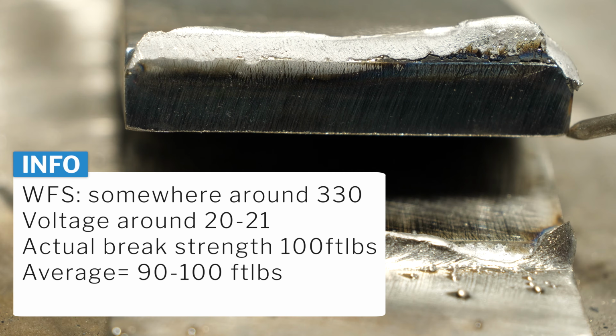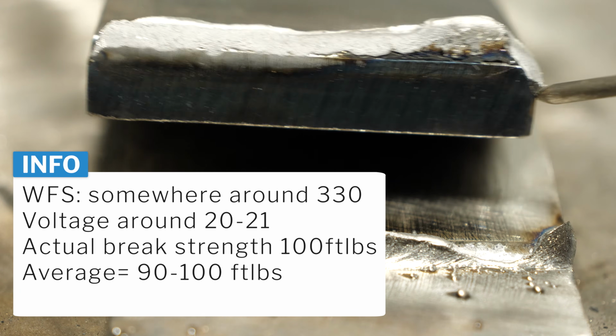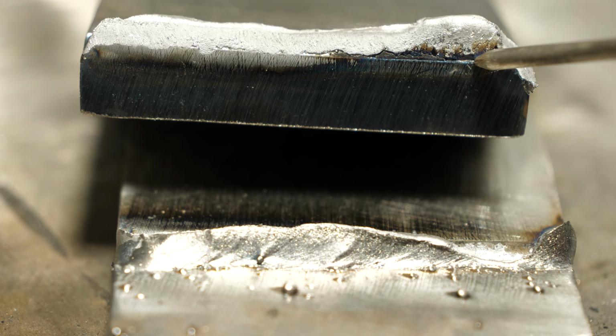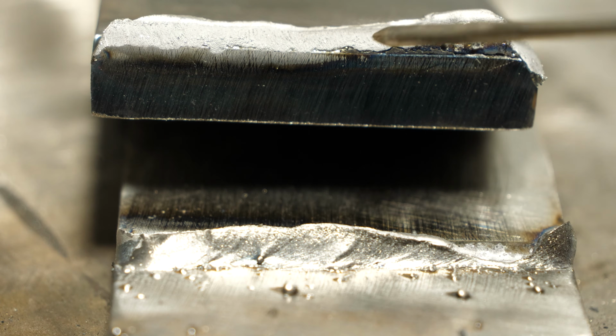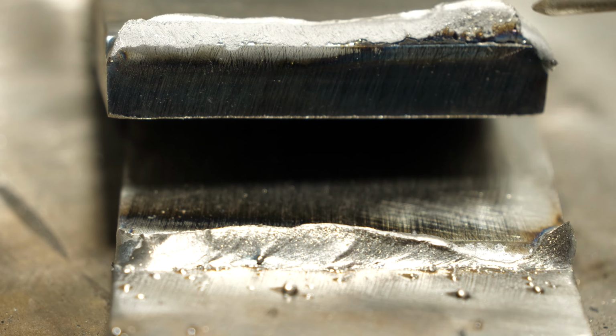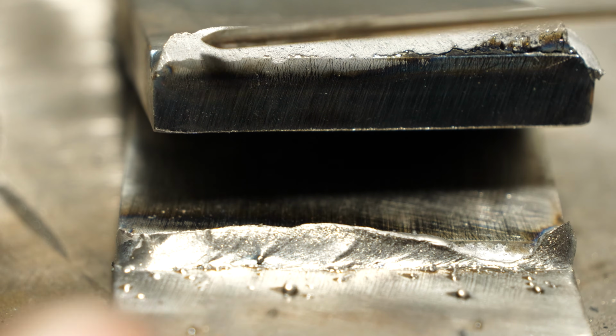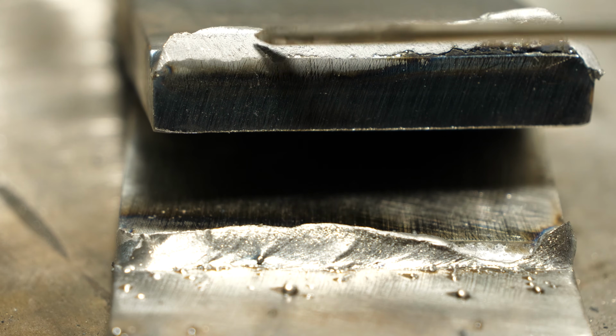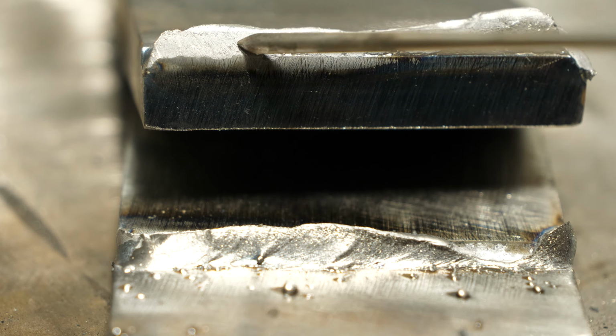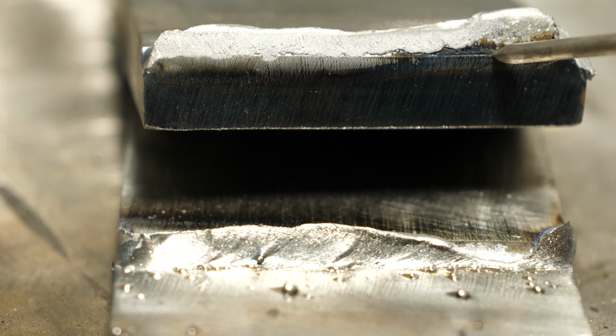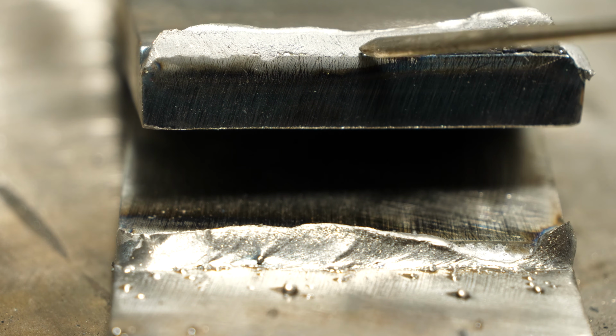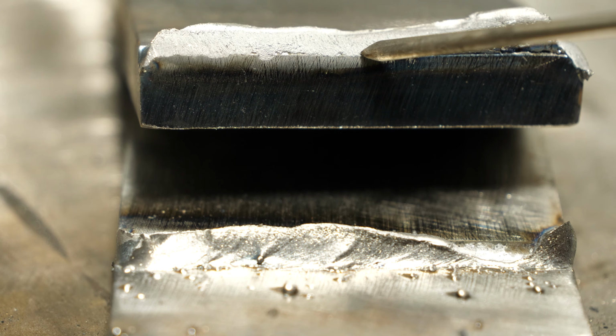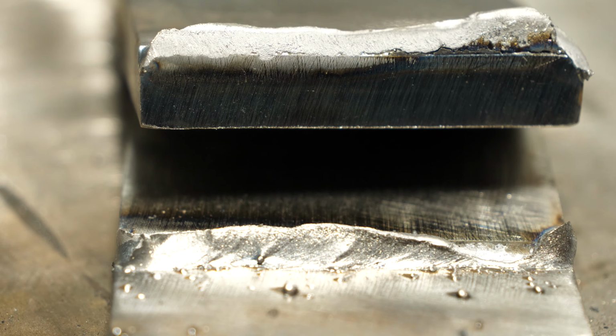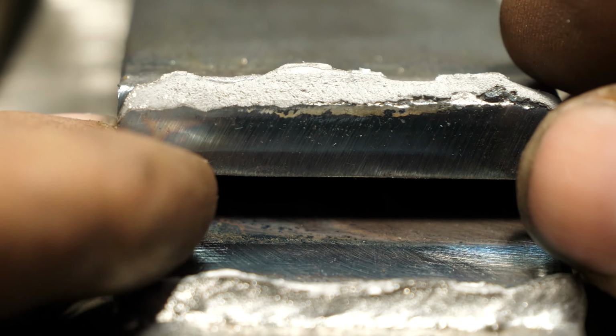Let's go over to this guy. This one was done with the same settings, just was not sputtering, and we can see the same deal here. No penetration or fusion at the start whatsoever. And then about halfway through, the plates got heated up enough to where there is some fusion. You can see that's what we want to see, where you have a clear line, no line. This is preferred. That means we had at least some root fusion, if not penetration. This is what you don't want to see. So it's about 50-50. This also posted higher strength numbers, and that is likely why. When you bend towards the face, the strength is higher when you have more penetration, and that's simply due to the mechanical advantage that the penetration provides. Now let's look at this.